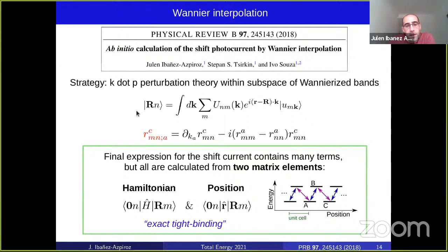Now, as a quick reminder, Wannier functions, which are denoted by lattice vector R, live in real space because they are given by a Fourier transform of the Bloch functions from reciprocal to real space. And here they use unitary matrices that mix bands. So in this sense, because of this real space structure, the Wannier formalism is very close to the tight binding formalism, actually. Now, it all consists of plugging this expression into the matrix elements and start collecting terms. There are many terms that appear, but at the end of the day, in the Wannier formalism, all of them can be calculated from just two matrix elements in Wannier basis.